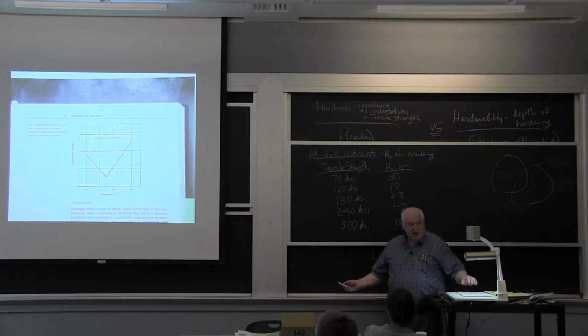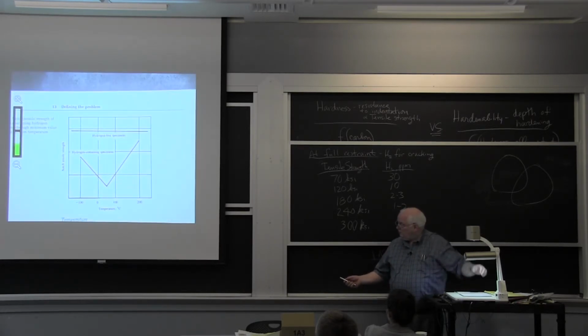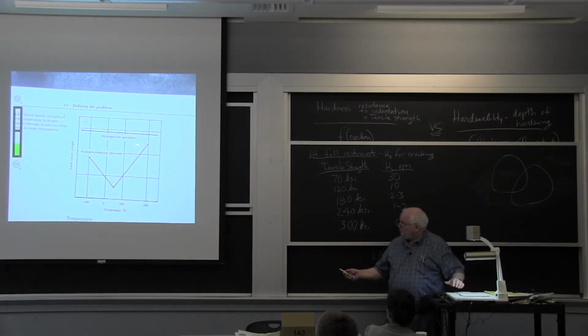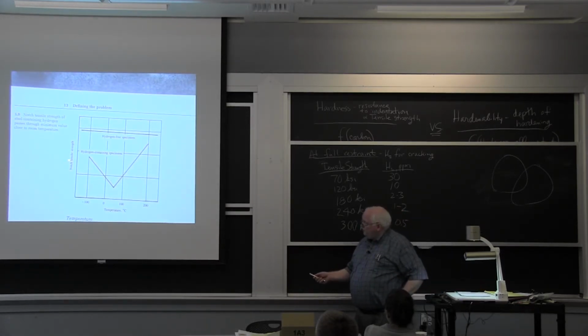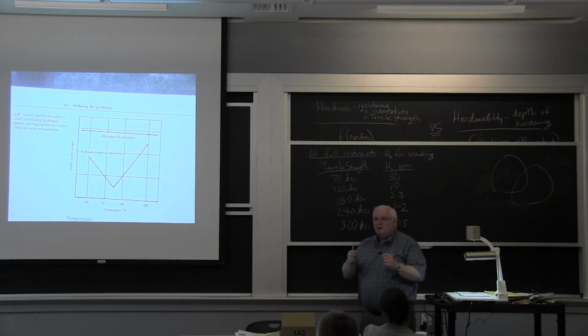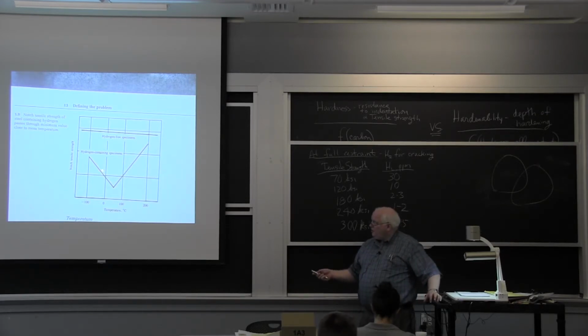This is out of Coe's book, and he shows temperature versus a hydrogen-free specimen, what they call a notch tensile strength. Well, the notch tensile strength is, am I ripping the piece of paper? If I have a notch or a welding defect, like in those Liberty ships, I had a notch which weakened the ship in a brittle material. A hydrogen-free specimen has no brittleness, no hydrogen embrittlement. If I have a hydrogen-containing specimen, it turns out the worst condition is right somewhere down here around room temperature.